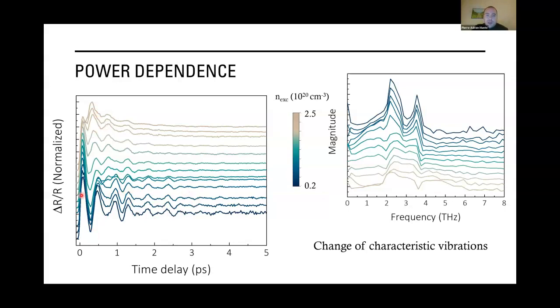And what we can observe is that there's a strong variation of the oscillation when we increase this power. We can see that the lifetime seems to be shortening, and we also see that this structure seems to disappear and leave place to another type of oscillating pattern. If we perform the Fourier transform, we can see a similar effect, where these two amplitude modes, especially the one at 3.6 terahertz, almost disappear to become an anti-resonance or Fano resonance for that matter.